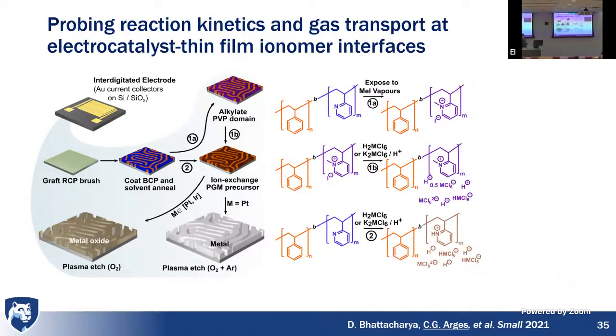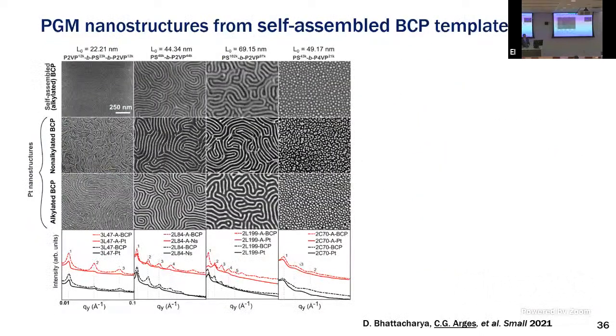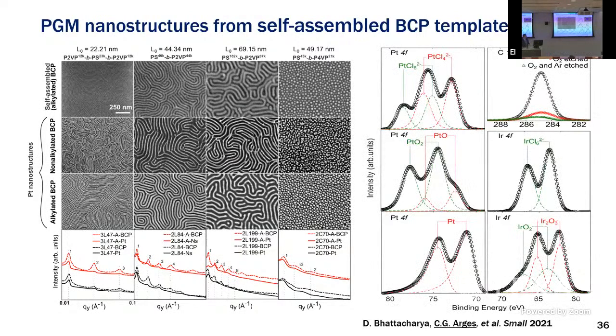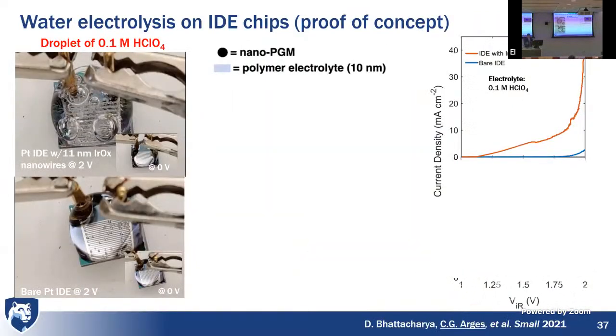We then use reactive ion etching to reduce the metal. And then in some cases, we get iridium oxide. If we're doing water electrolysis, this is fine. If we want the oxygen reduction, we get platinum oxide. We reduce the platinum oxide to platinum with argon plasma. And so we put this thin film of nanocatalysts on this interdigitated electrode. So I'm going to skip over this, but this just shows here our block copolymer transferred into electrocatalysts with different morphologies on these interdigitated electrodes. We can monitor the evolution of this chemical structure with XPS. Nobody had done this before. We were worried, will this work?